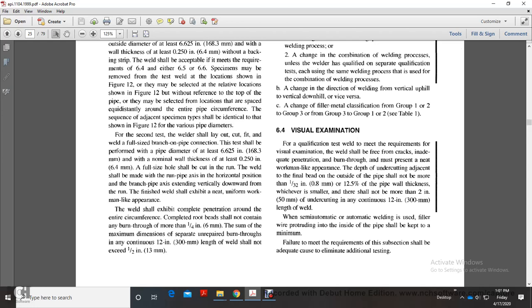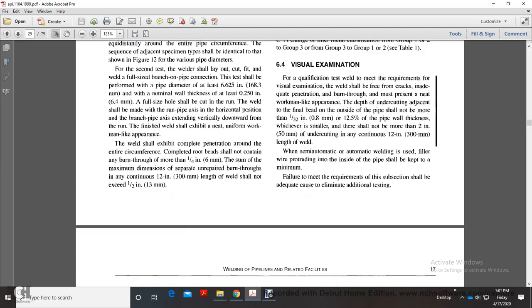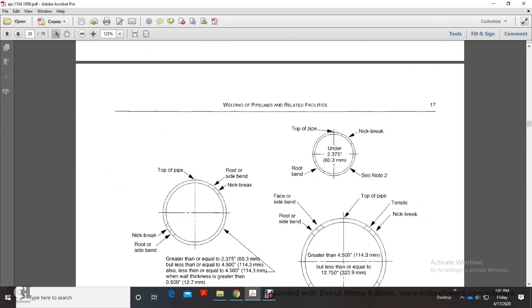Depth of undercutting adjacent to the final bead on the outside of the pipe shall not be more than 1/32 of an inch or 12.5% of the pipe wall thickness, whichever is smaller. There shall not be more than 2 inches of undercutting in a continuous 12-inch length of the weld. With semi-automatic or automatic welding, the filler wire protruding inside of the pipe shall be kept to a minimum. Failure to meet the requirements of this subsection shall be adequate cause to eliminate additional testing.